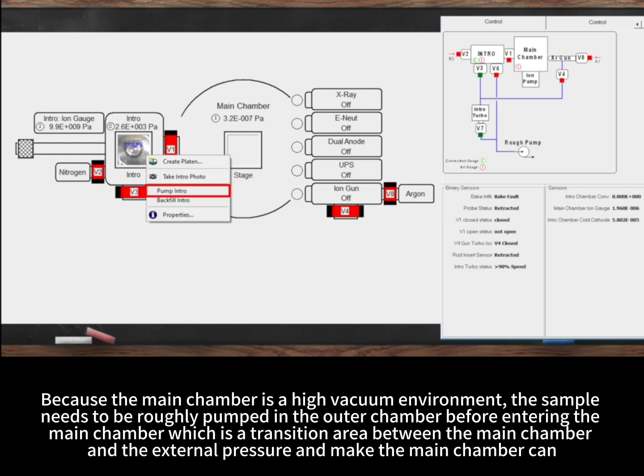Because the main chamber is a high vacuum environment, the sample needs to be roughly pumped in the outer chamber before entering the main chamber, which is a transition area between the main chamber and the external pressure, and makes the main chamber able to be maintained at a certain pressure even if the sample is in and out.